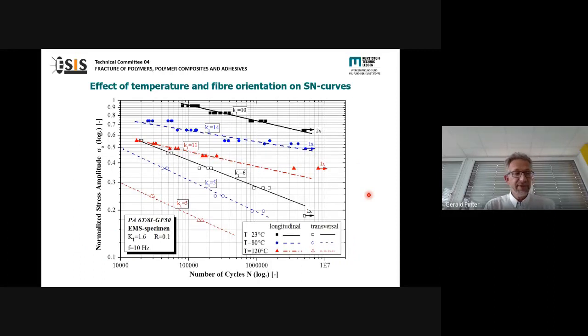For example, you can see in this diagram the effect of temperature and fiber orientation in the short fiber reinforced polymers. You can see here in black, in red, and in blue the effect of the temperature. Of course, if you do the test at higher temperatures, you get much earlier failure. So you see here 120 degrees Celsius, 80 degrees Celsius, and 23 degrees Celsius.